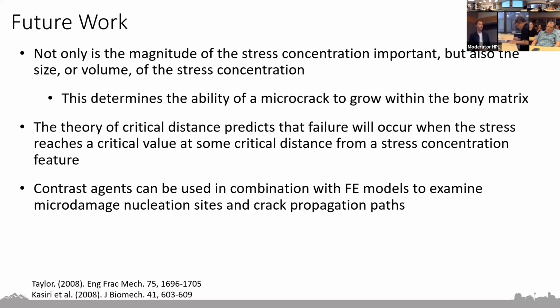So I think moving forward, we have a lot of things we still want to explore. If we want to stay at the material level, I think if we want to predict failure, it's not only important to know the magnitude of these stress concentrations, but also the volume of material subjected to this elevated stress, because that's what's going to determine the ability of a crack to grow within the bony matrix. So although cracks may initiate in a really small region of highly stressed material, it probably won't propagate as far because it's going to quickly reach the boundary of the stress gradient.